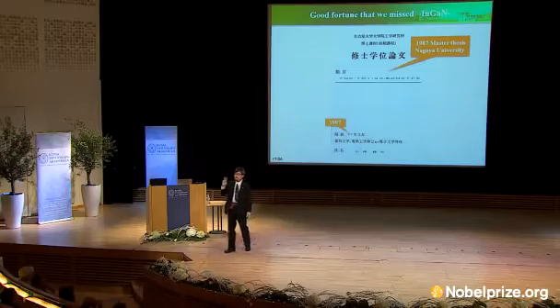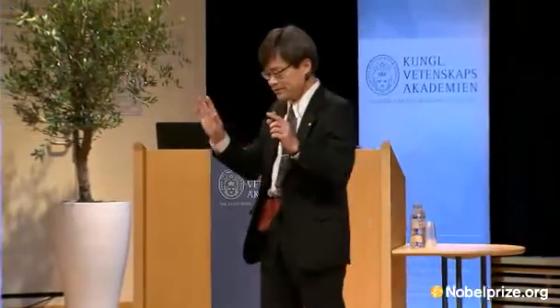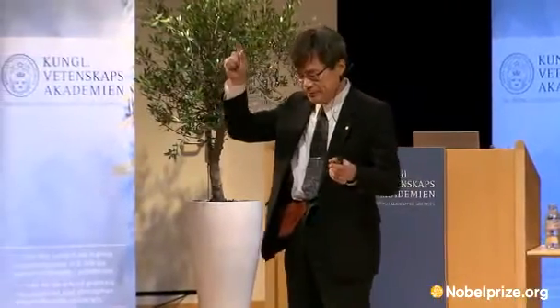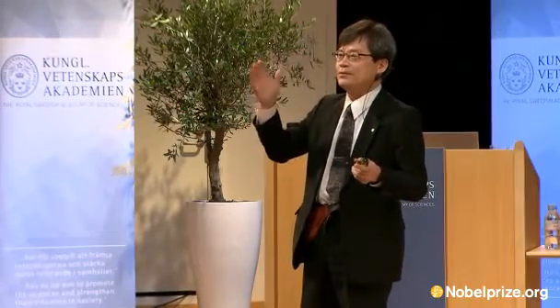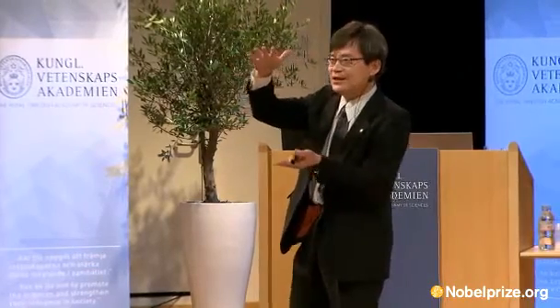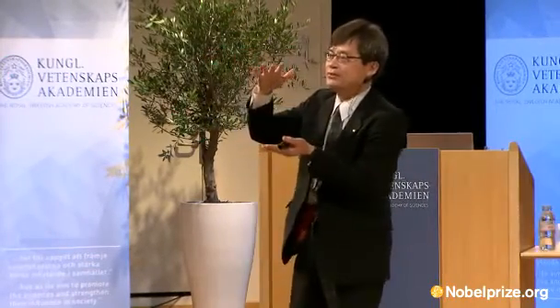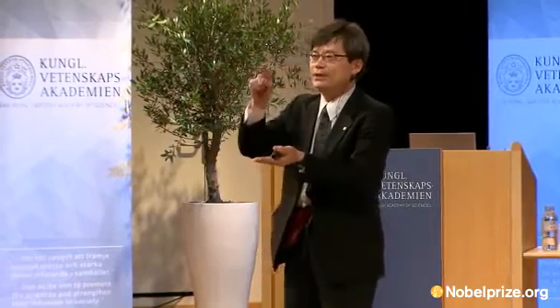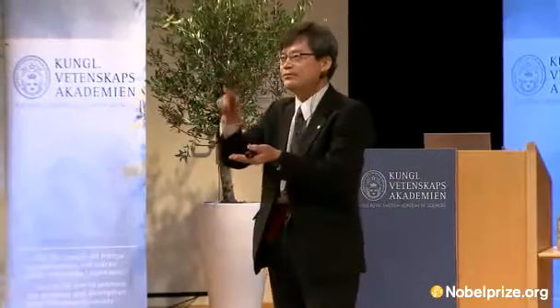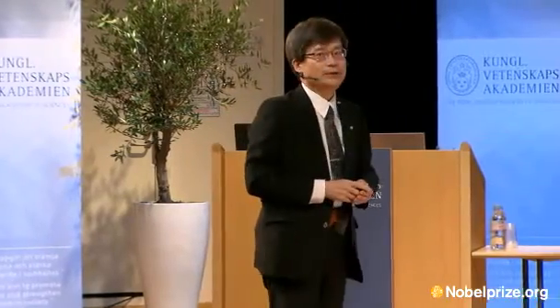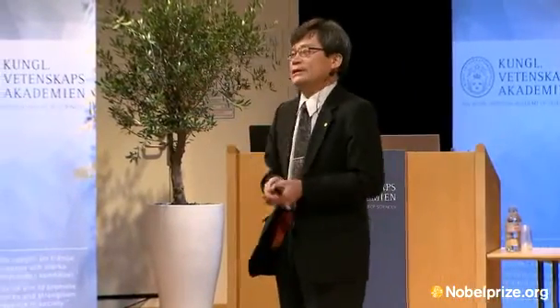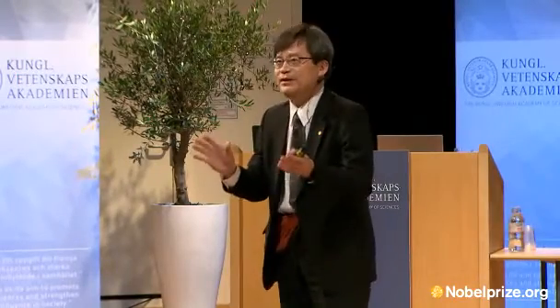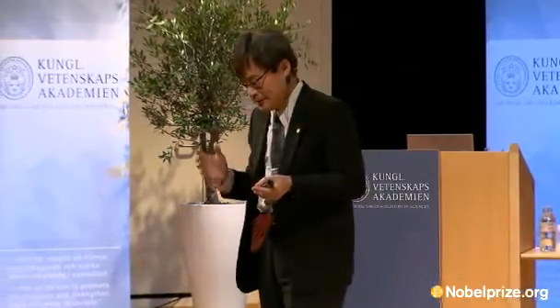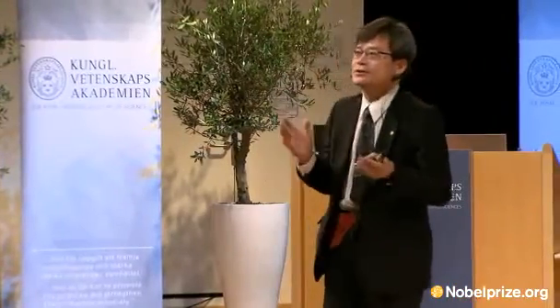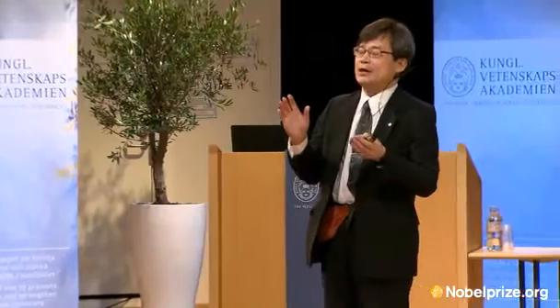We still had the problem of blue emission. The band gap of gallium nitride is in the UV region. For blue emission, we need to grow indium-containing alloys, indium gallium nitride. Of course, we tried to grow indium gallium nitride, but it was also very, very difficult. So we grew indium gallium nitride with an indium content of less than 3%, for which the band gap is still in the UV region.